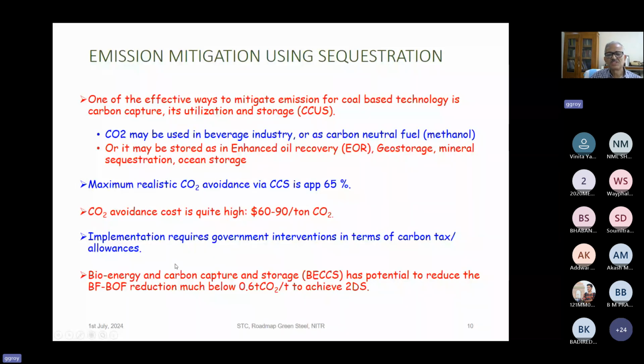Bioenergy and carbon capture and storage basically has the potential to reduce the emission much below 0.6, and it can easily attain 0.6 ton of CO2 per ton of crude steel to achieve the 2DS. Okay, so it is possible if you use bioenergy, that is the biomass, and also carbon capture and storage, and all these things.